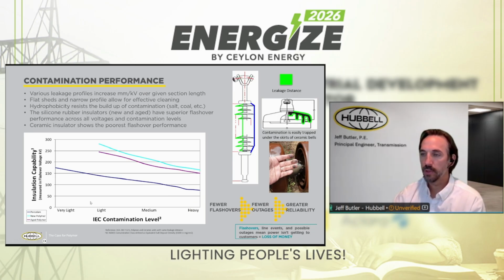And then the bottom line is a porcelain bell string, and basically what we saw is across the full range of contamination, we saw superior flashover voltages on the polymer insulators than their porcelain equivalents. And these were equivalent leakage distances. So we matched the leakage distance of the ceramic string to the leakage distance of the polymer insulator, and we saw higher flashover voltages. Now, what does that mean?